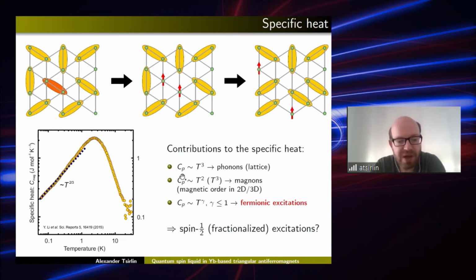For example, if the specific heat is due to phonons, then it should be T cubed. If we have magnons in an antiferromagnetically ordered state, it will be T squared or T cubed, depending on the dimensionality. But if we have linear or sublinear behavior, that is quite unusual for magnets. Well, of course, it's not unusual for metallic systems because metals also show a linear contribution to the specific heat. But this compound is a very robust insulator with a band gap of maybe 4 eV, so we for sure do not expect any electronic contribution. But if we see something linear or sublinear in the specific heat, it immediately indicates unusual magnetism.